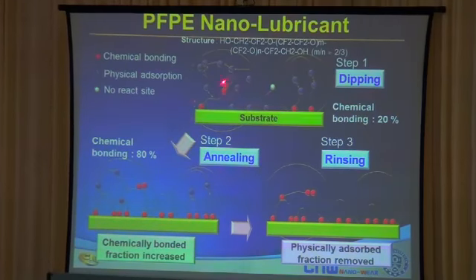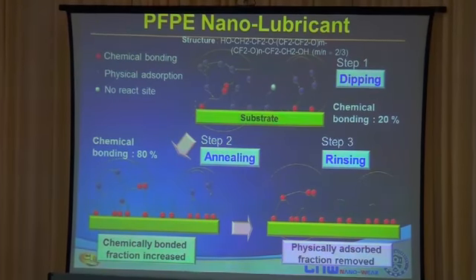It turns out that the percentage of these mobile molecules is important, because if the lubricants are removed from the track due to some contact, you'd have to replenish. In other words, the lubricant should be able to flow back and fill in that location. So the percentage of this physically bonded lubricant is important, but if you have too much of it, it will again pose some problem. Now, how do you control the percentage of this physically bonded lubricant?